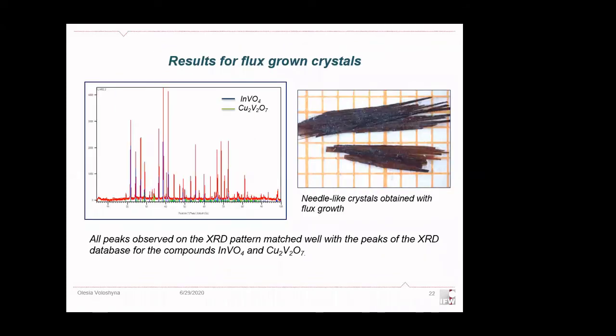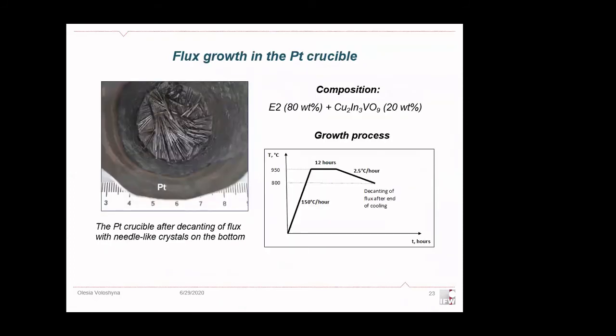But interesting that we still obtained some crystals, and XRD analysis of these crystals showed that we obtained a mixture of indium vanadate and copper pyrovanadate in it. So the next step was preventing the interaction between our melt and the crucible.